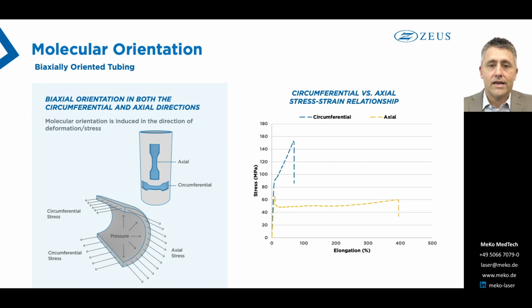So enter biaxial orientation. So biaxial orientation now is orientation along both the axial axis, like we've talked about so far with drawn fiber, but now also the circumferential axis. So if you perform a tensile test on dog bone specimens that are cut as shown in the picture there, you have an axial oriented dog bone and a circumferentially oriented dog bone, you will get stress strain curves that look like that on the right.